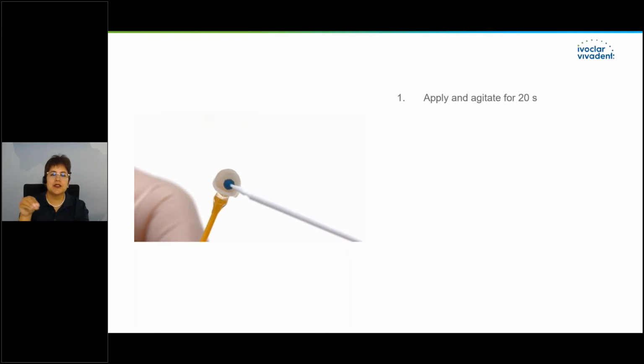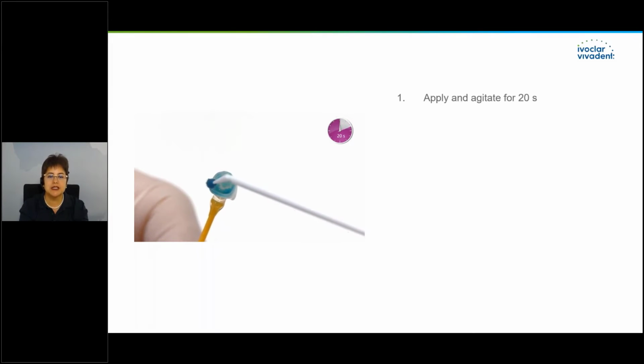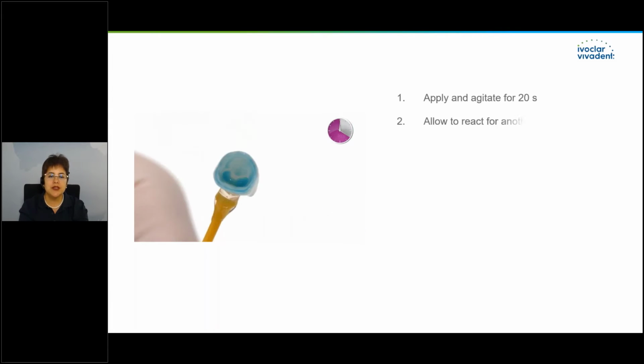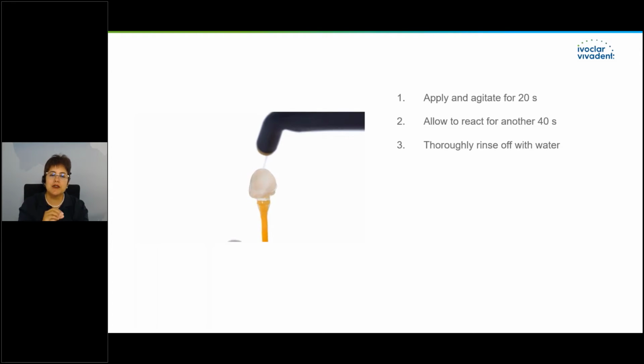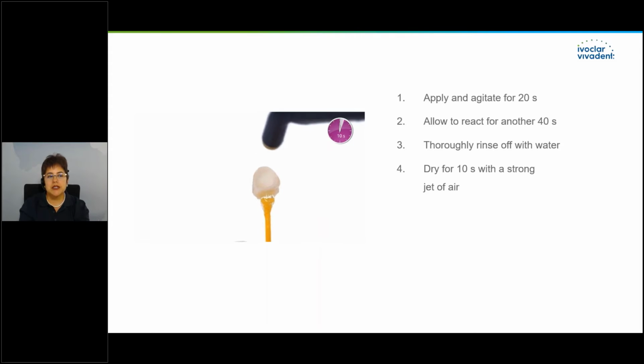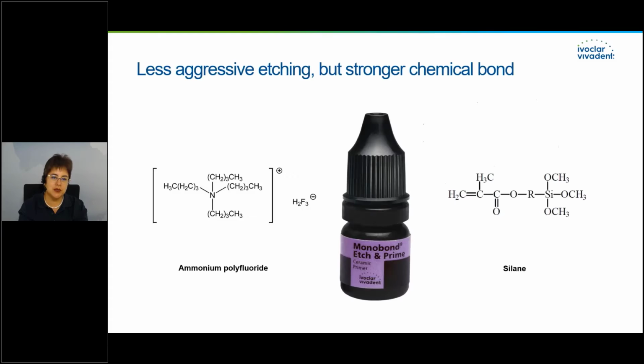So clinically, after the try-in, we will rinse the restoration and we apply Monobond Etch and Prime for 20 seconds. We just have to scrub it in and then we leave it to react for 40 seconds. It is crucial to wait the time. Afterwards, we rinse with water and then we dry for 10 seconds. So then we will add our cement, like Variolink Esthetic, and then we will follow their instructions for use.